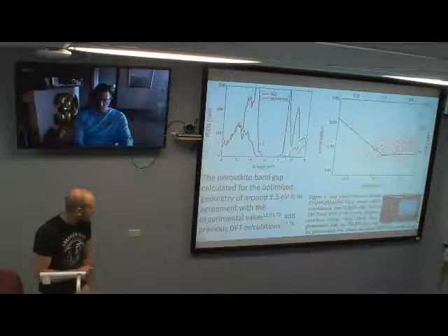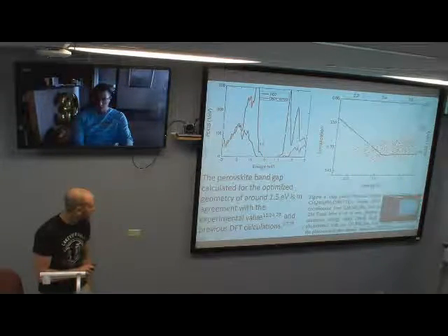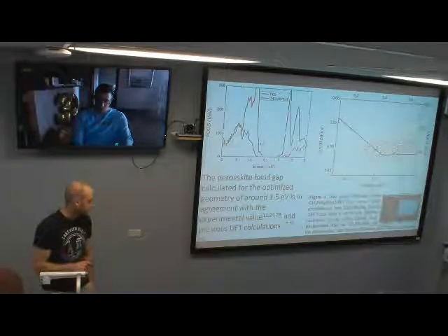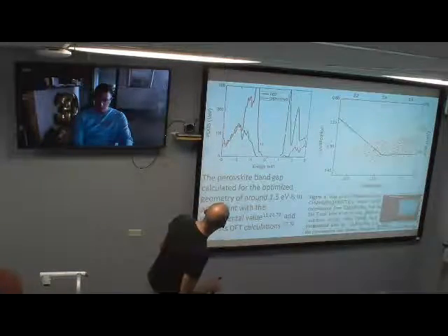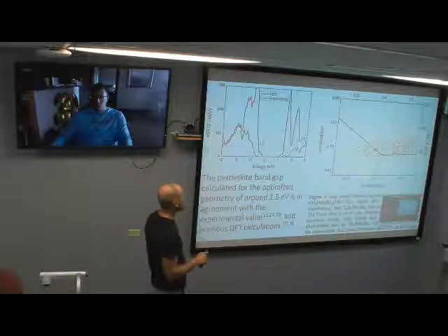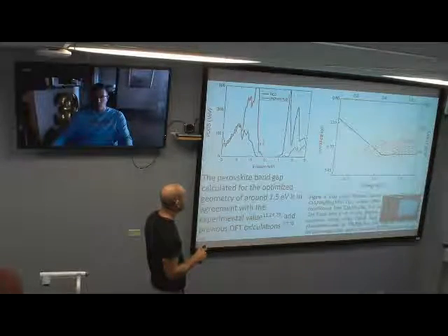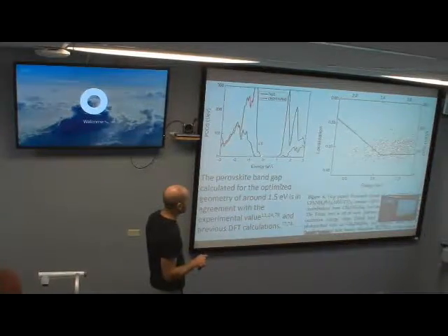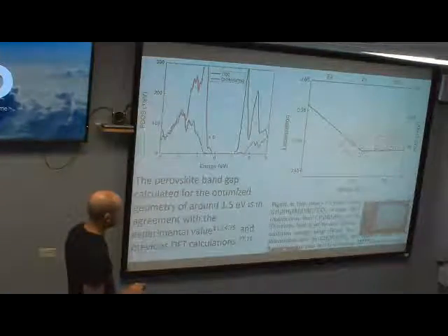Okay. So the red line is your methylammonium perovskite. The black line is representing titanium dioxide. And I'm colorblind, sorry. Okay, yeah, so basically you have these two different densities of states. Your perovskite has a higher valence band edge than the titanium dioxide does. But the titanium dioxide has a lower conduction band edge than the perovskite does. So this is the situation that you want.